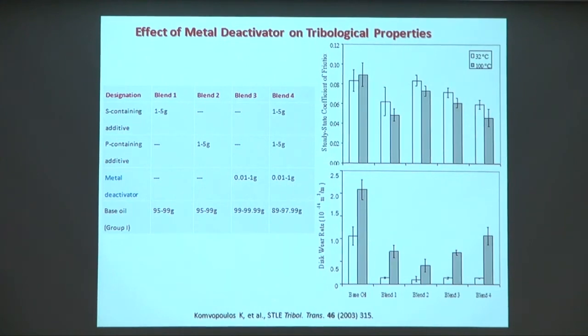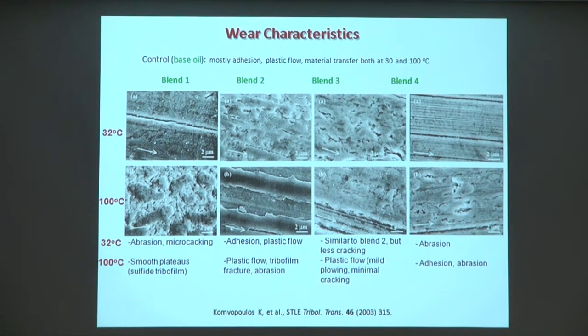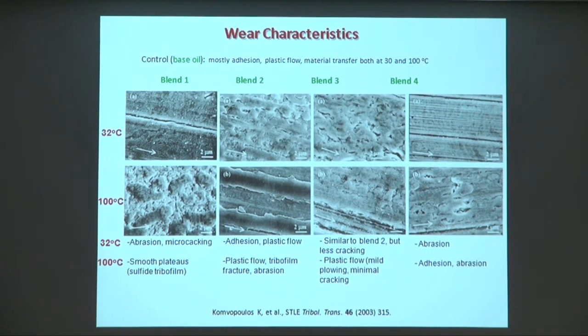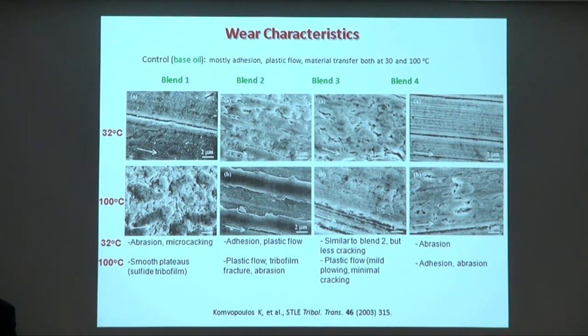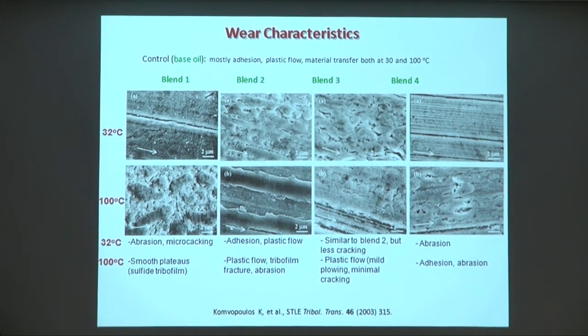So again, we have replaced one of the elements that we want to remove from these additives to improve emissions. And this gives us some further idea of the formation of these films. Again, recognizing that once we change the chemistry, the reactions that take place with the sliding metal surfaces can cause different wear mechanisms to take place.